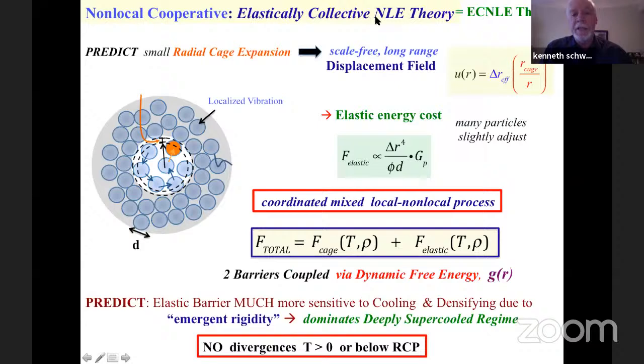And so this then leads to the elastically collective NLE theory, or the ECNLE theory, in which the activated event involves some local hopping on a cage scale, but with the active participation or facilitation by a dynamic fluctuation of particles outside the cage. So the small cage expansion leads to a scale-free long-range displacement field given by this expression. It falls off as a power law, that's what scale-free means, and the amplitude is predicted from the dynamic free energy. So then if we sum up all the displacements in the far field, there's an elastic energy cost that we associate with the barrier.